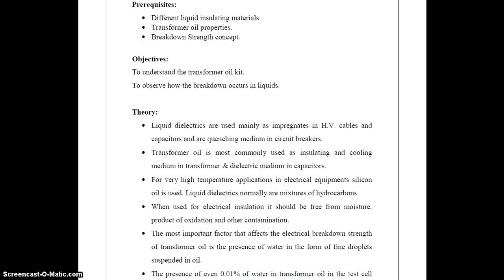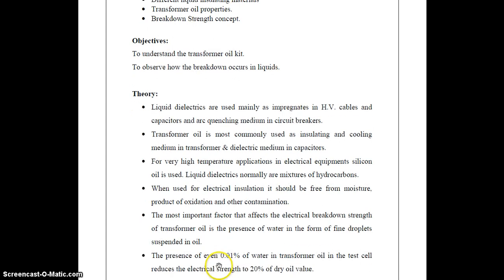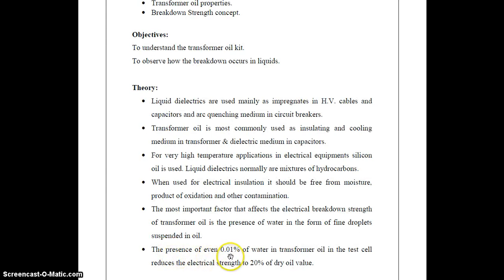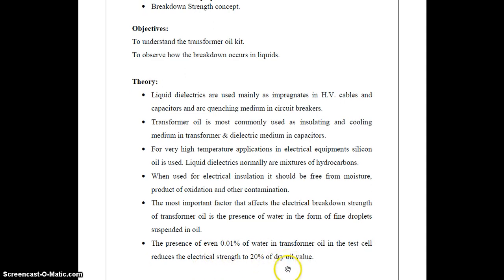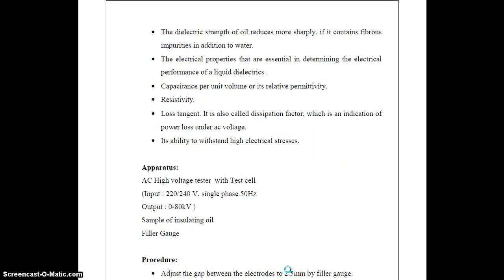For electrical insulation, the oil should be free from moisture, products of oxidation and other contamination. The most important factor that affects the electrical breakdown strength of transformer oil is the presence of water in the form of fine droplets suspended in oil. The presence of even 0.01% water in transformer oil reduces its dielectric strength to 20% of the dry oil value. The dielectric strength of oil reduces more sharply if it contains fibrous impurities in addition to water.